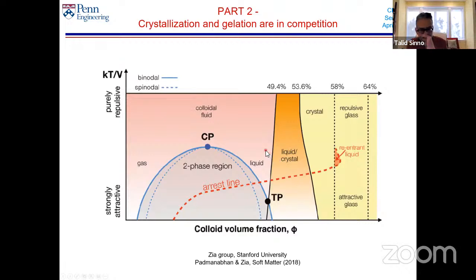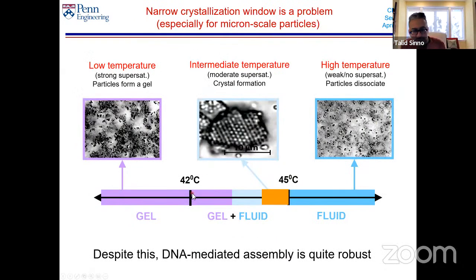So let me skip this little bit and just briefly mention a second phenomenon that I wanted to talk about. One of the problems with all of this, and I mentioned this at the beginning, is that because of this very strong temperature dependence, these crystallites are pretty hard to form. You've got to cool your sample really slowly, otherwise you'll form a gel. So there's a tiny window for crystallization. If you stay at high temperature, there's no aggregation. If you go to low temperature, you form a gel. And there's a tiny little window where you give the particles enough time to rearrange and form a crystal. This is particularly bad when you use large, micron scale particles. Not such a big problem for nanoparticles, but definitely a big problem for micron scale particles.